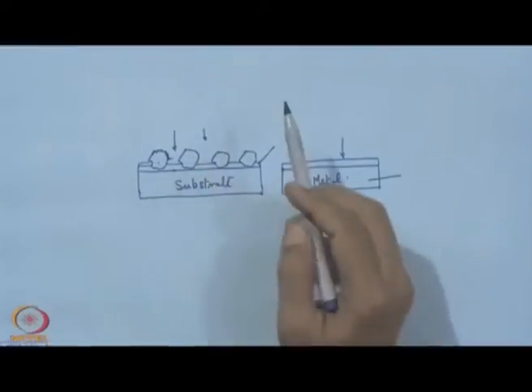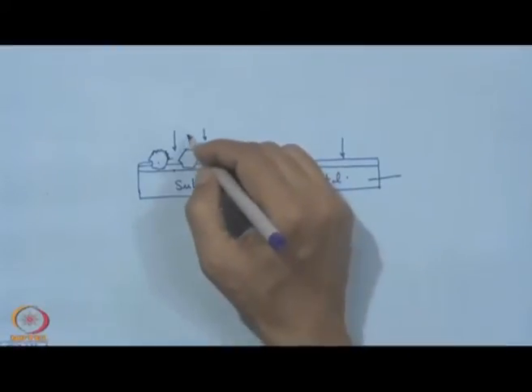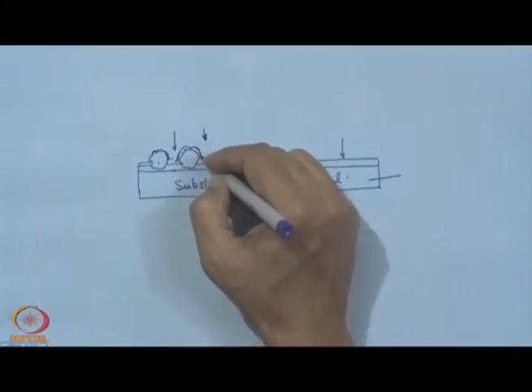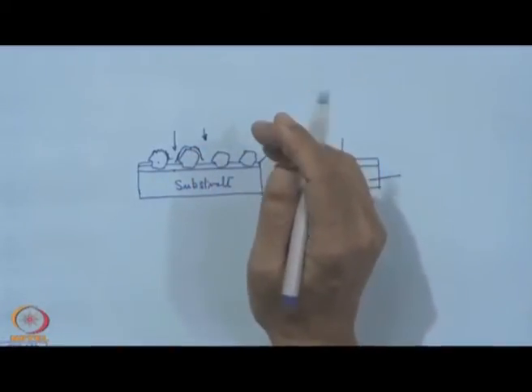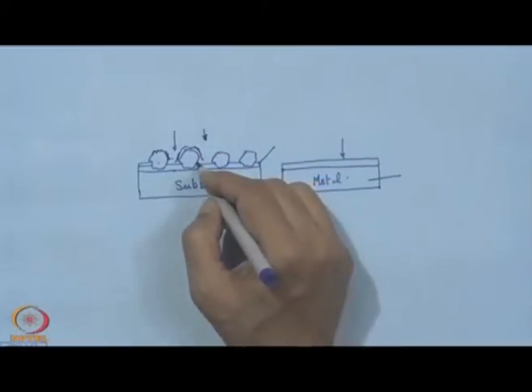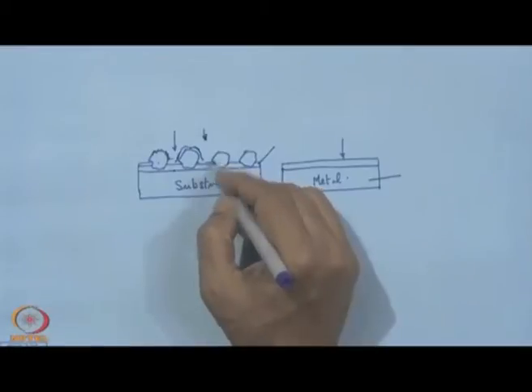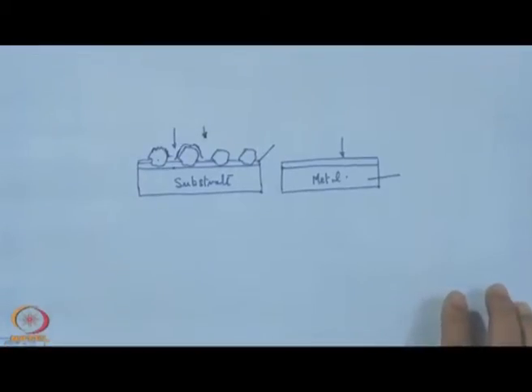And if this conducting path is created when this is placed on the substrate, then there is every risk that the metal which is not supposed to sit on this surface will deposit over it, and in certain extreme situations it can cover the grit wholly or partly, and there will be heavy metal deposit. Ideally, metal deposit should be only in the space between the grits and not on the grit. So, in this case what has to be done? A special treatment is necessary.